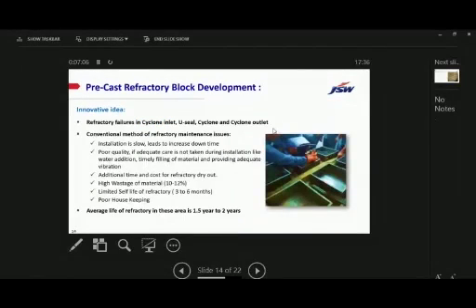Yes, precast refractory. Actually, CFBC boilers consist of a high volume of refractories. It is about 1650 metric tons of refractory in a unit. So there are high failures of refractory and high work on the refractories. Our conventional casting of the refractory has some major issues. Its installation is so slow and leads to high MTTR, and it is quite tough to maintain the quality because it is highly man-oriented work. So adequate care cannot be taken.